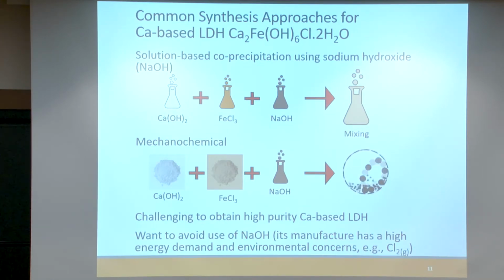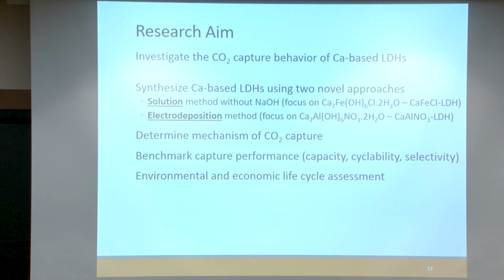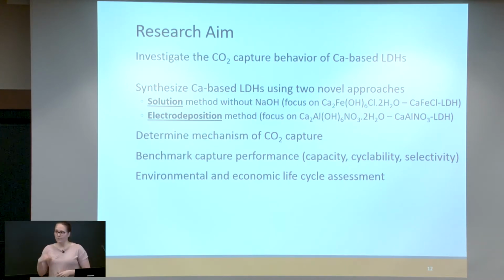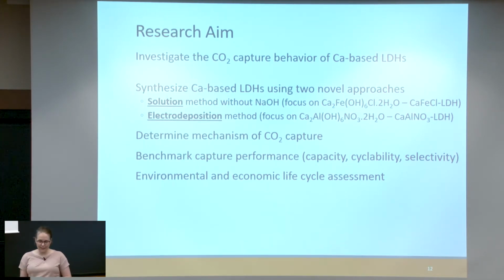So if we're thinking about a material that when you manufacture it, it doesn't have so many concerns in terms of environmental toxicity, we really want to avoid the sodium hydroxide. So what we've been doing is synthesizing these calcium-based layered double hydroxides using 2 different approaches. One is a solution method without any sodium hydroxide in there. It's complicated to try and just obtain the layered double hydroxide, but I'll hopefully convince you that we understand why we can obtain the phase-pure layered double hydroxide. And then the second method is what's known as an electro-deposition method, which is using electricity to make the layered double hydroxide.